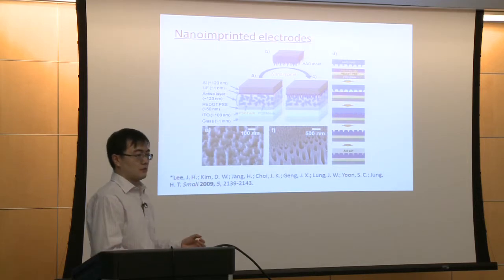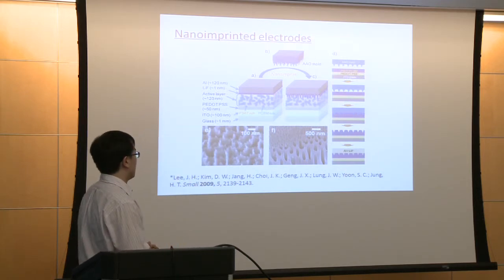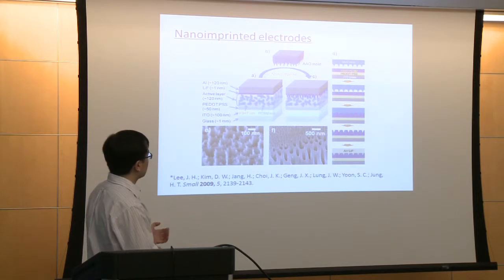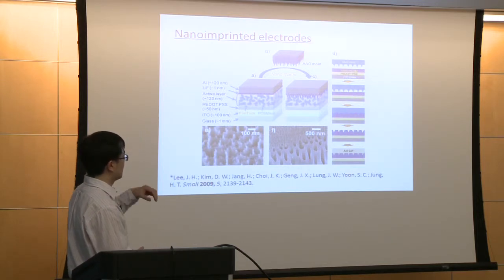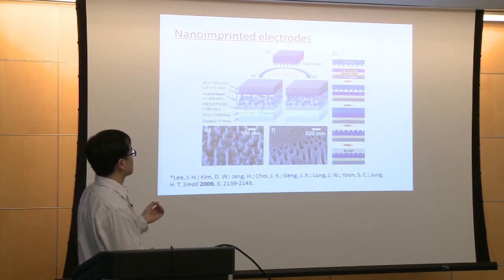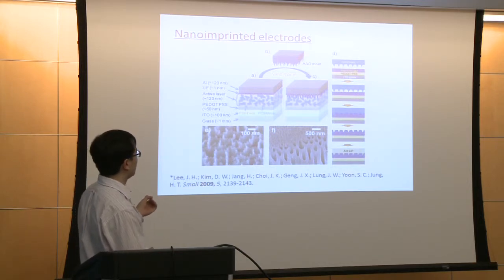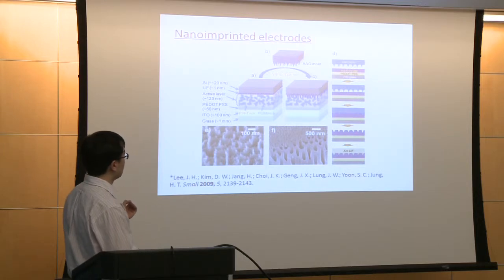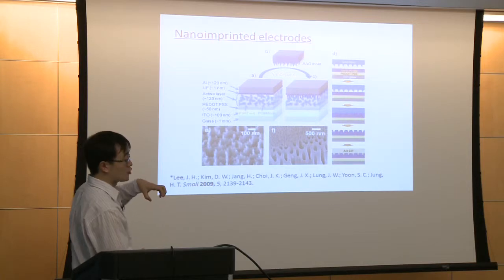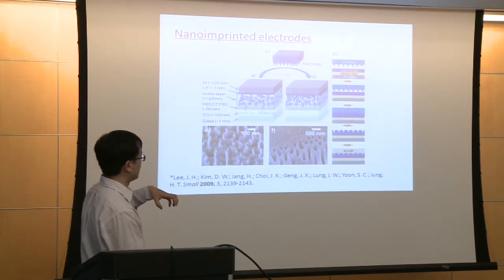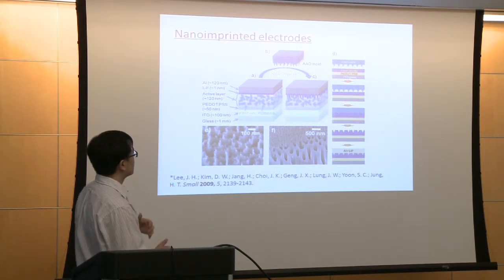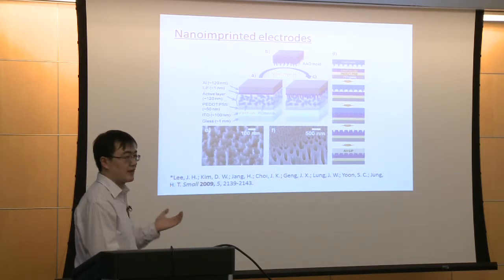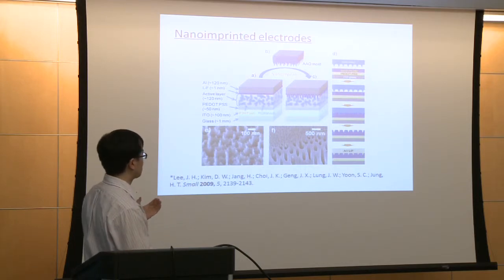So in order to solve the problem here, one group in Korea tried to nanoimprint the electrodes into the active layer. They used the AAO mold, which is anodic aluminum oxide mold. They insert the electrode into the active layer to shorten the conduction pathway between the electrons and holes and the electrodes. So this can somewhat enhance the efficiency of the solar cell.